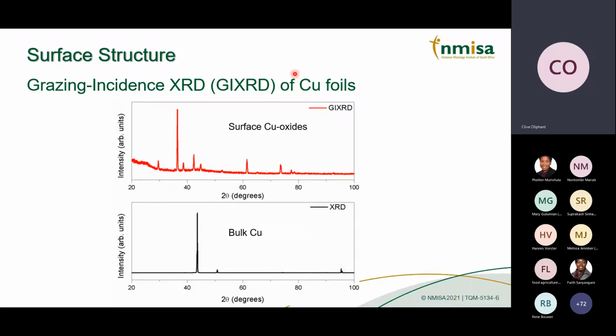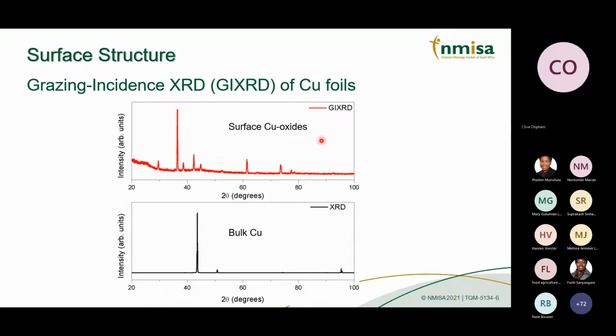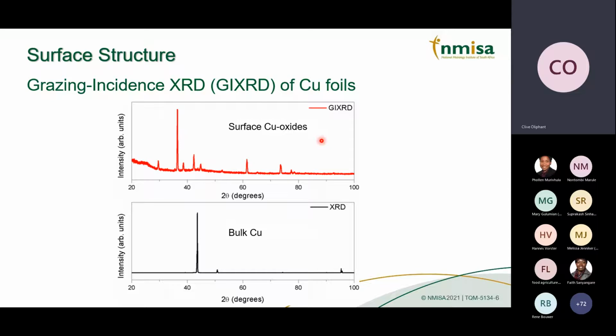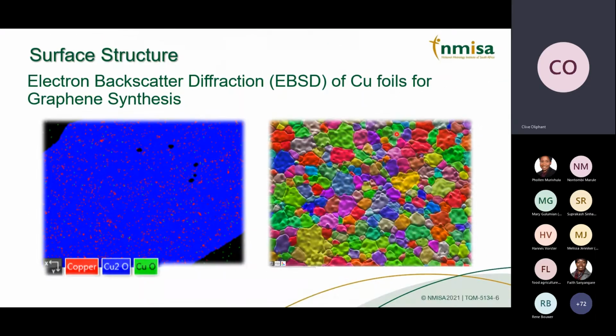So we need to bear that in mind, that if we want to synthesize graphene, we need to stabilize this, and we can treat the surface with hydrogen, it is possible. So then we can get just the pure copper surface, basically.